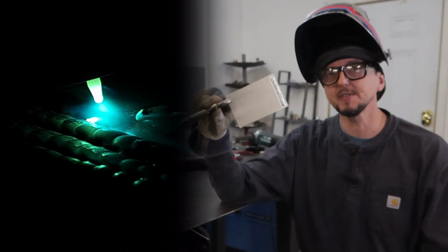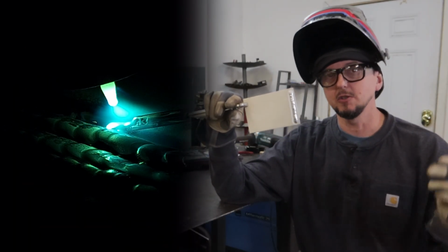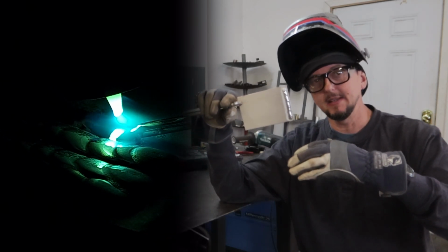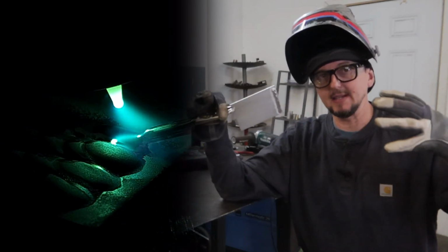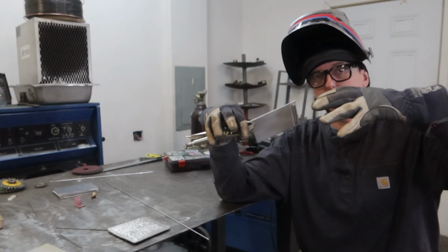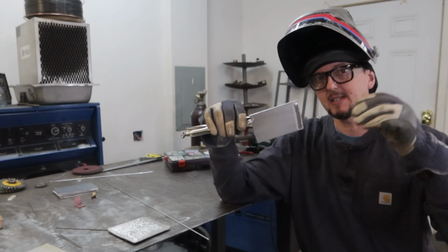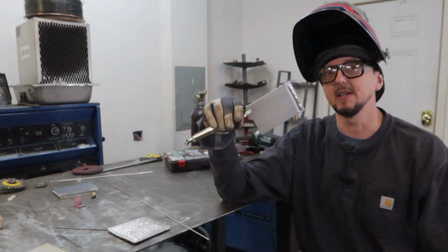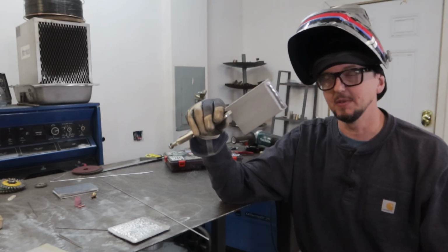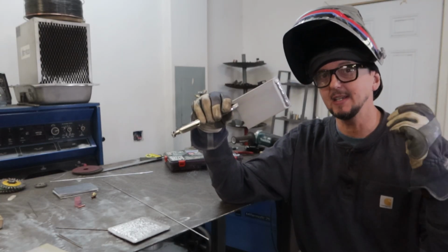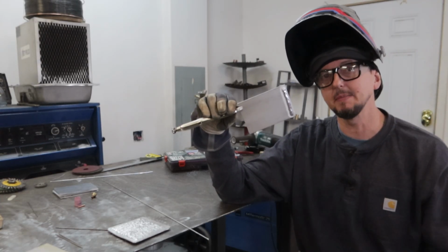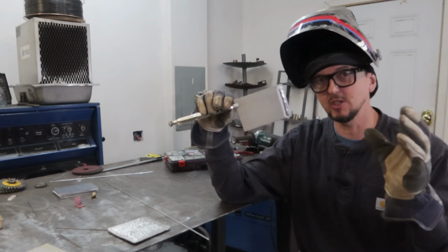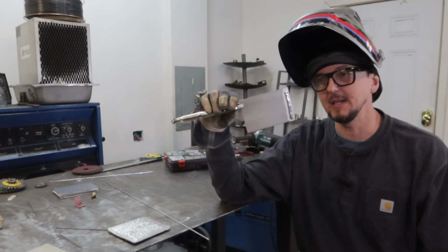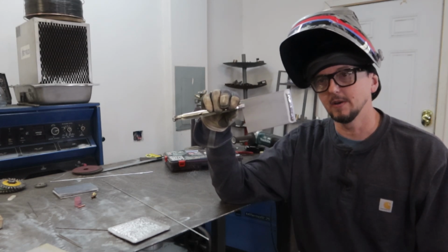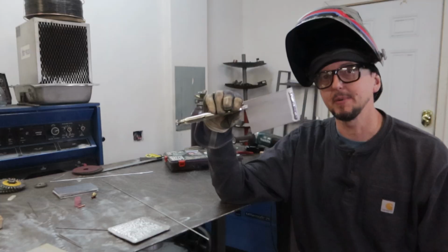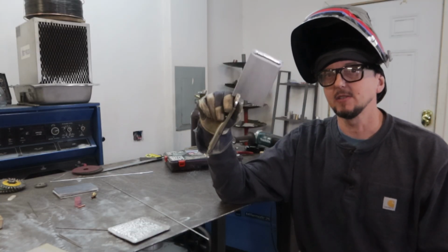Okay? Also, watch your tungsten. As you dip into the weld pool, the hot aluminum is going to expand in size. So when you dip into the weld pool, that weld pool is going to come up. And if you're too close with the tungsten, it'll actually hit your tungsten. And that's very common when you first start welding aluminum as well. So if it comes up and it hits your tungsten and contaminates it, just stop and go clean up your tungsten, because as soon as you start to see that shape change on your tungsten and it gets real contaminated, you're not going to be able to control your arc very well. And so you might as well just stop and go clean up your tungsten, okay? All right, so those are the two things to watch.